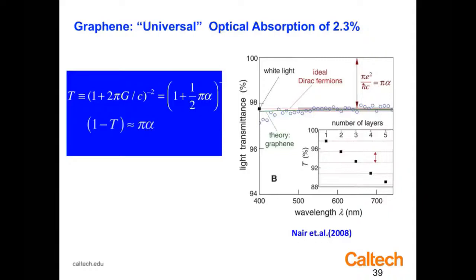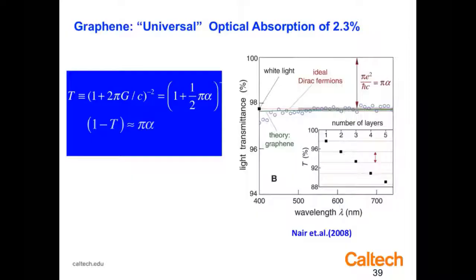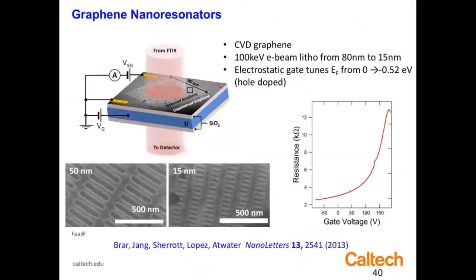So we were motivated by the idea, could we actually, instead of making graphene interact relatively weakly with light, create 2% absorption, could we absorb 100% of the light in a sheet of graphene? That seems like a fairly big challenge here. This is 2%. So one way we can do this is to make graphene resonators. Since graphene is two-dimensional, we make ribbons, and if we excite them with a polarization transverse to the ribbon, that acts electromagnetically similar to the metal nanoparticles that I showed you in three dimensions. They support dipole-like electromagnetic resonances.